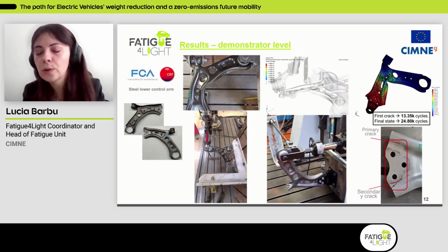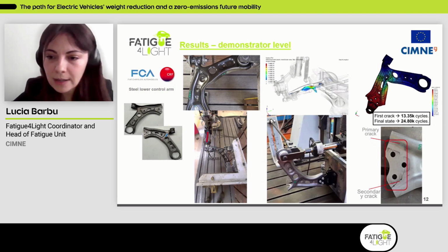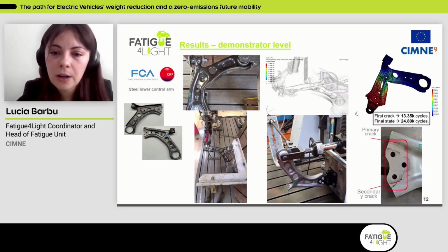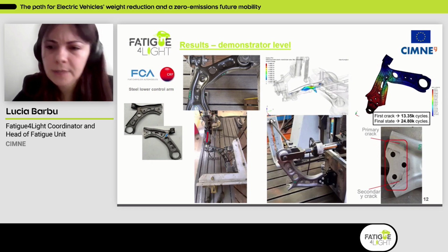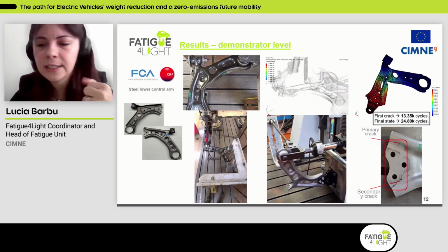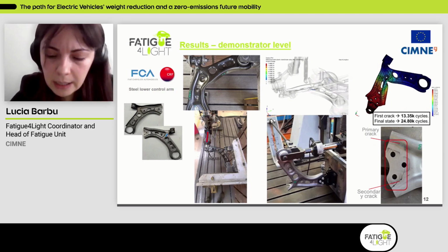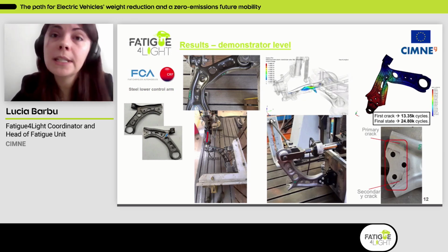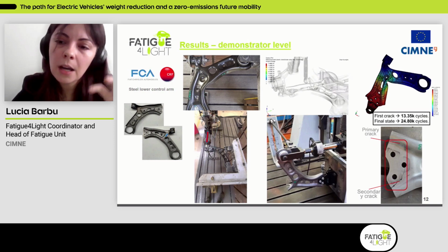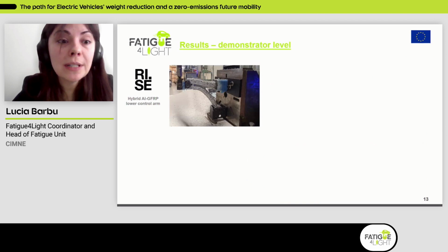Here, I'm just showing you an image of one of the failures that were observed on the steel lower control arm, where a very interesting mode of failure was observed with the primary crack and then the development of a secondary crack that finally completely broke the specimen. Later on, you will see how, from the numerical point of view, we managed to capture this crack propagation. Okay, let's go to the next demonstrator.